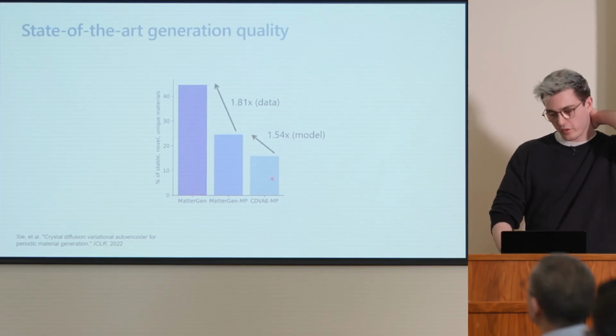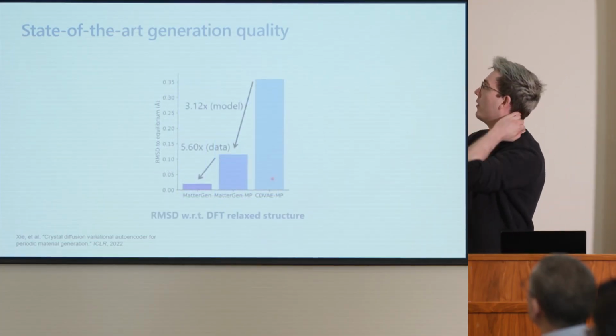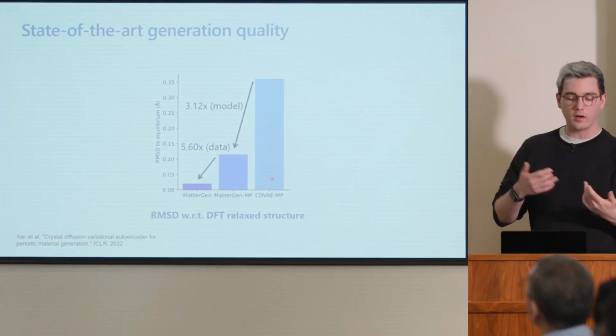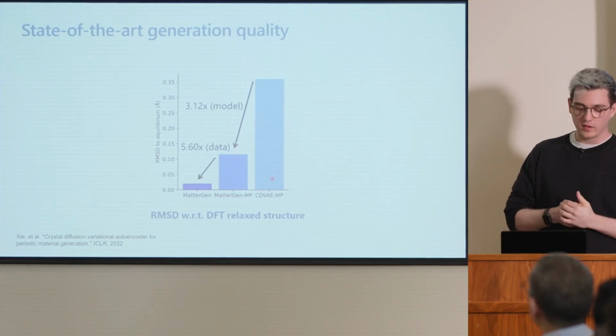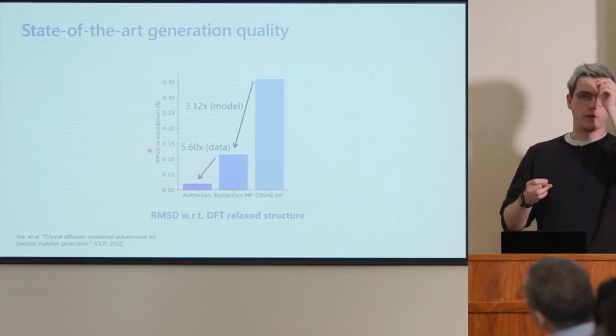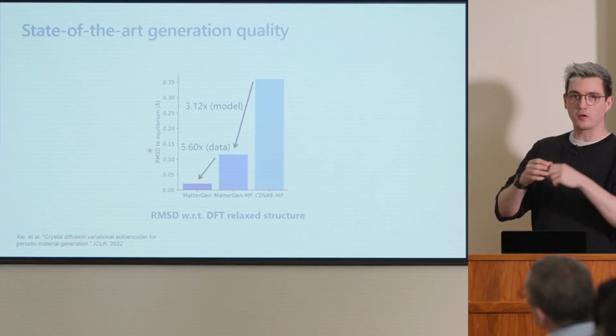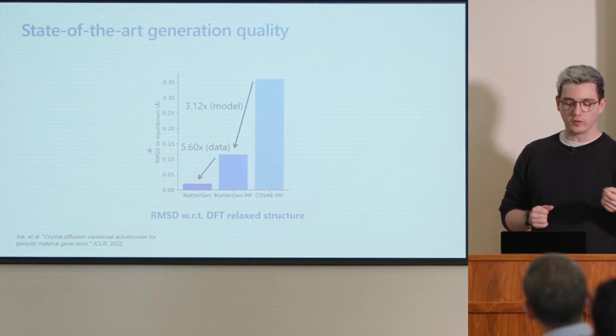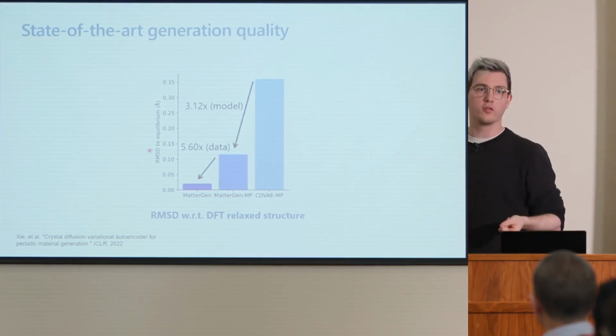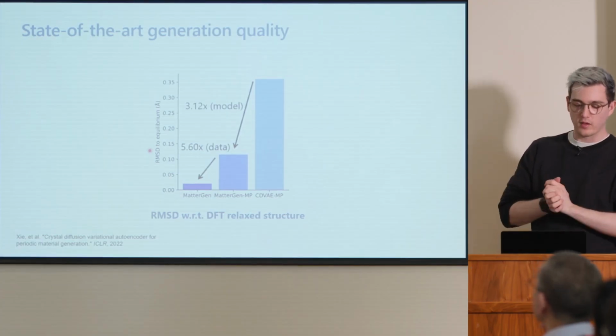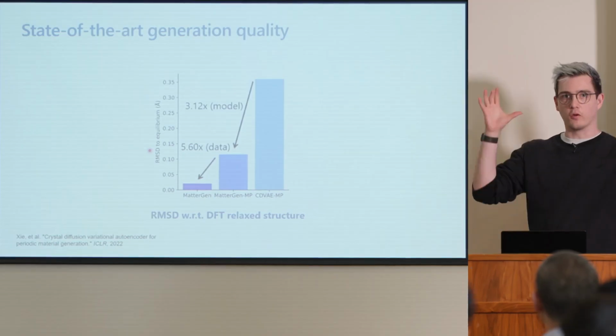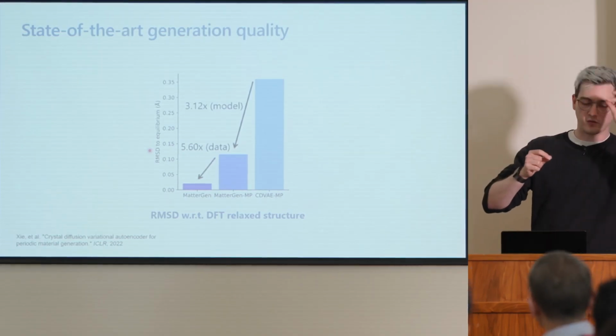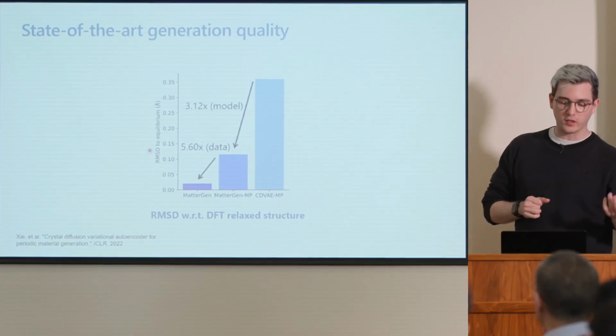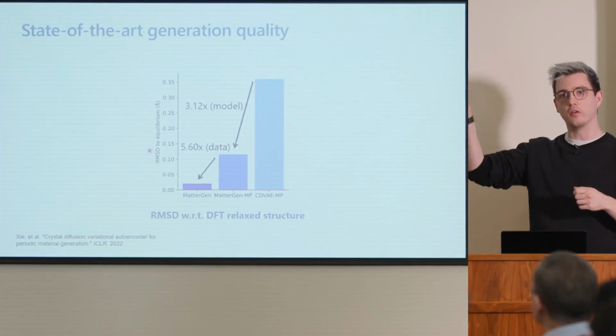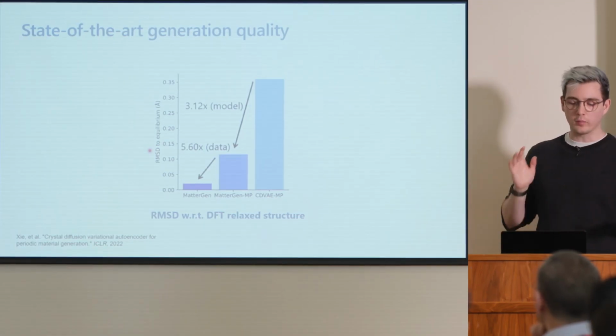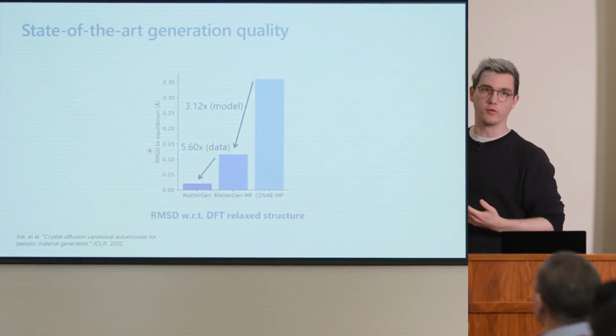And then another measure that we looked into that tries to measure what's the quality of the materials that we generate is the root mean square deviation from the relaxed structure. So what does it mean? Our model just comes up with a 3D material. The next thing we do is we throw it into our computational workflow, DFT, which is quite expensive, and that first relaxes the structure to its lowest energy state. So it just follows the forces to find the equilibrium structure. And then, of course, you can ask how far away from this equilibrium structure was your initial proposal. And the closer you are to the final equilibrium, we argue the better is the initial proposal, of course.